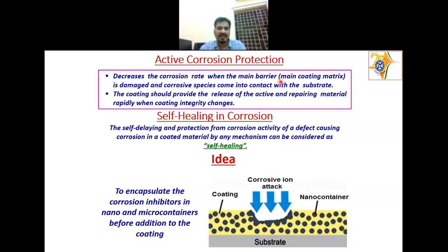So the active corrosion protection is that it decreases the corrosion rate when the main barrier, the main coating matrix, is damaged and corrosive species come in contact with the substrate. So when the barrier property is breached, then a protection comes into play. That protection is known as active protection. The coating should provide release of the active and repairing material rapidly when coating integrity changes. A kind of self-healing.